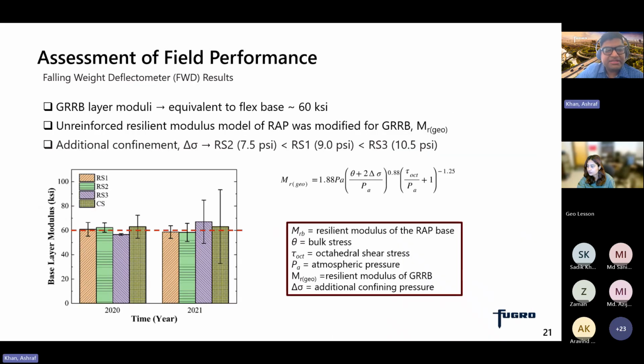And when we look at the results from the falling weight deflectometer, it shows that the geocell reinforced RAP base layer had an equivalent elastic modulus compared to the flex material. And not only that,